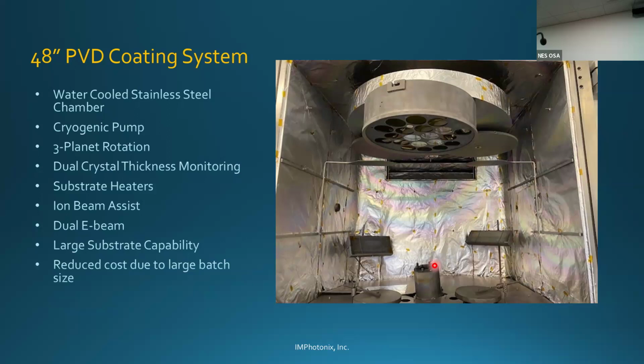What's happening on the crystal is, as the film is condensing, you're not measuring the thickness, but you're measuring the change of frequency. The Inficon microprocessor would take that change of frequency and go through its lookup table algorithm. You have to tell it, I'm depositing aluminum oxide. And it would say, oh, you're depositing aluminum oxide, the frequency is changing by X amount, therefore it must be this thickness. Because they're calibrated size crystals, there's a certain surface area, and the microprocessor tells you the thickness from the algorithm that translated the crystal frequency change.